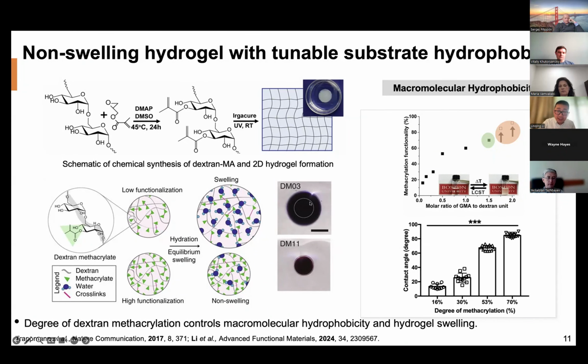you can control swelling. The dotted line is the dimension of the hydrogel before swelling, and by mixing different ratios together, you can actually make the hydrogel non-swelling. The major issue for the hydrogel community right now is that when a hydrogel swells significantly over the course of cell culture, you change not only the pore size, the diffusion of nutrients, but also the mechanical properties. So you don't have the original properties you wanted, and the final properties are significantly different. What we wanted was hydrogels with minimum or no swelling that maintain not only the mechanical properties but also the physical structures.